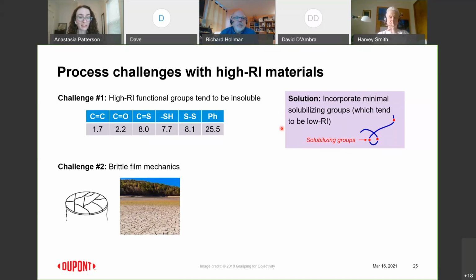Another challenge is that a lot of these materials that tend to be high refractive index also tend to have poor mechanical properties. So we were working with our customer and looking at our different materials, and they noticed in their fabrication process there was a lot of cracking on the wafer. And so that's something that obviously is not very good for an optical sensor to have cracks throughout it.